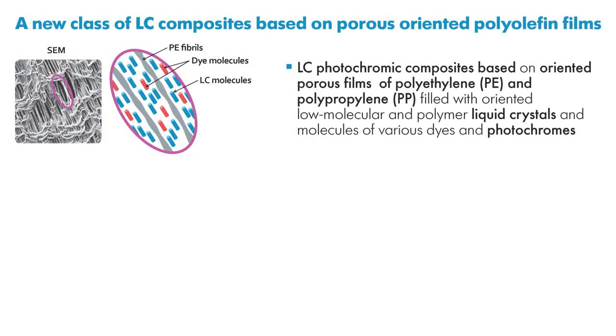We have obtained a new type of liquid crystalline composites based on porous oriented films of polyolefins. For the first time, we have used oriented porous films of polyethylene and polypropylene as polymer matrices. These films were filled with low molecular mass and polymer liquid crystals, including the molecules of various dyes and photochromes. It was found that the fibrillar structure of such polymers aligns the molecules of liquid crystals and photochromes. This allows the creation of unique photosensitive materials.